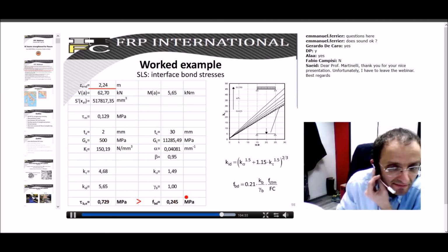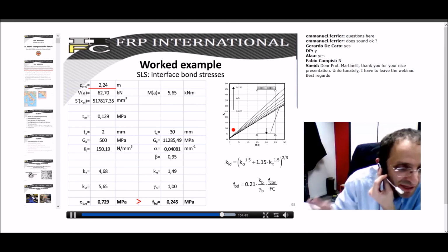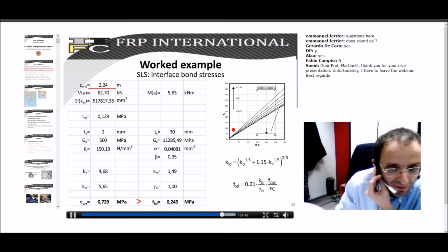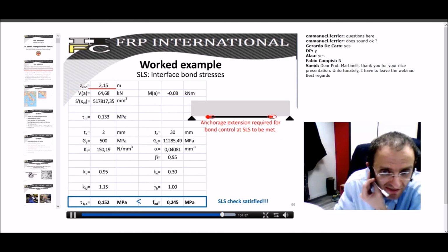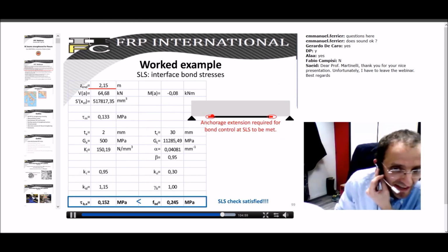And this tau is higher than the one allowed by the code. So this means that we have a too stiff interface, but we cannot change it. But we have a too big value of A, of the distance between the cutoff section and the theoretical support. So what we can do, we can try to just extend the anchorage to reduce A.